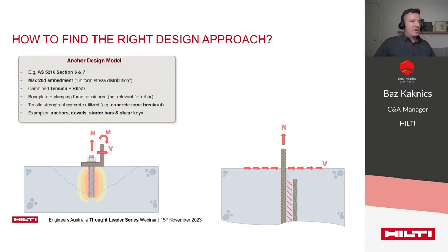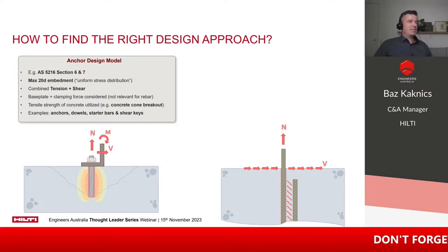In summary, the main goal of my presentation today was to help understand the differences between the anchor and rebar design theories. In certain cases, rebars may be designed based on the principles of anchor theory, for example, when they are used as shear keys or dowels, and the embedment depth is not greater than 20D, as we discussed earlier. Designers might also use this design method for shallow embedded starter bars, where concrete cone failure is expected and therefore